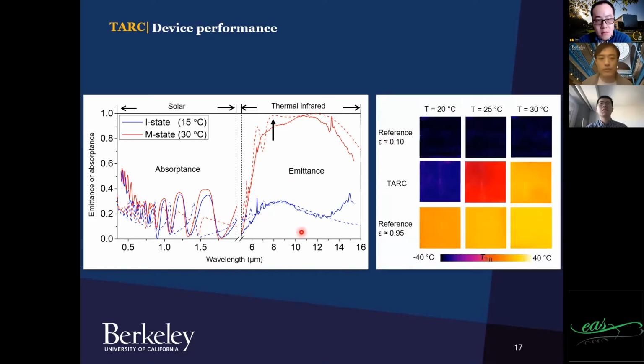And this can also be verified by an IR camera. The IR camera is designed based on the Stefan-Boltzmann law, so it will capture the power radiated from a remote object for remote temperature measurement. So if you use an IR camera to look at a piece of aluminum foil with a small thermal emittance, the readout will be super small, like -40 or something. However, if you use that to measure the temperature of tape with a thermal emittance close to 1, you will accurately get its real temperature.